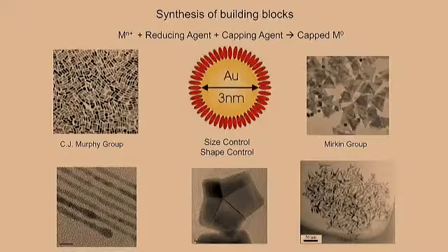So the interesting thing is that we have another important ingredient in this whole thing, what is called a capping agent. If you do not have any capping agent, we just keep on reducing the metal, uncontrolled growth will happen, and we get no specific size or shape that forms. So typically we add a third reagent, called a capping agent, that goes and sits or sticks itself to the surface of the growing crystal, and that basically gives you the shape. Okay, so that's the overall idea. But the point is this, with a very, very small change. Of course, many times the reducing agent itself can serve as the capping agent. Okay, so in many cases the capping agent and reducing agent are one and the same.